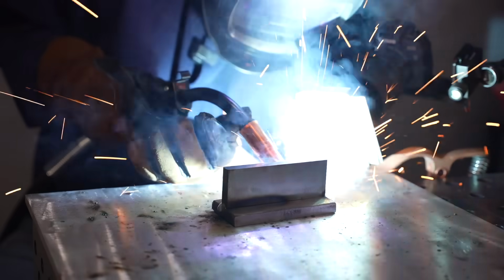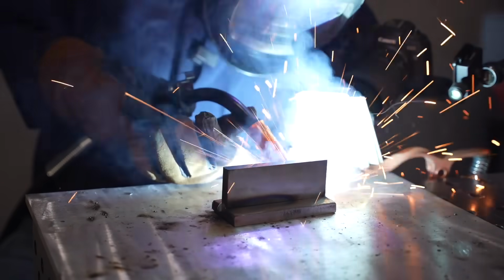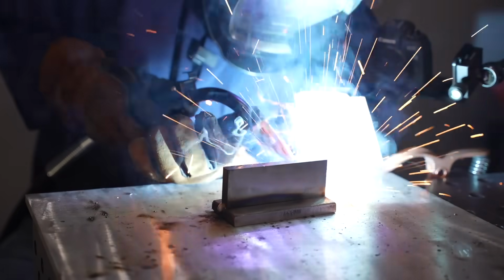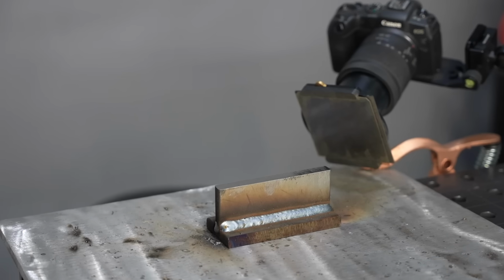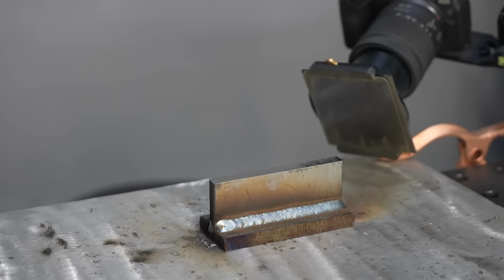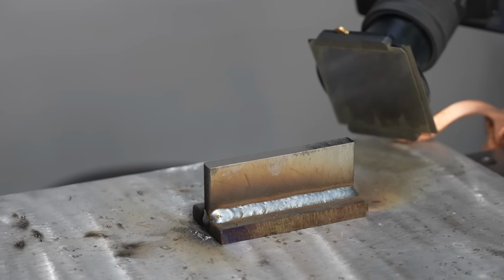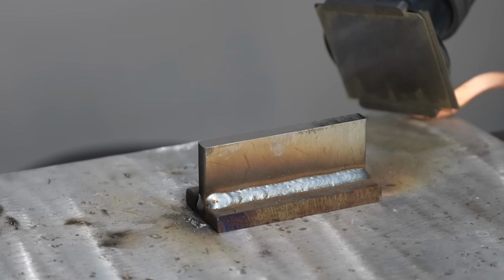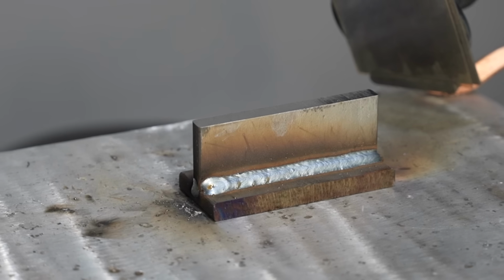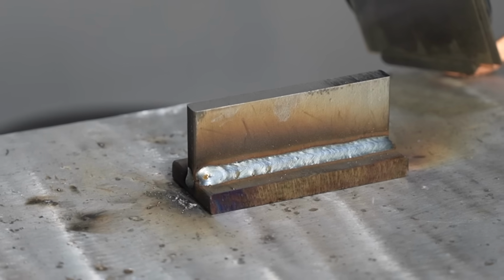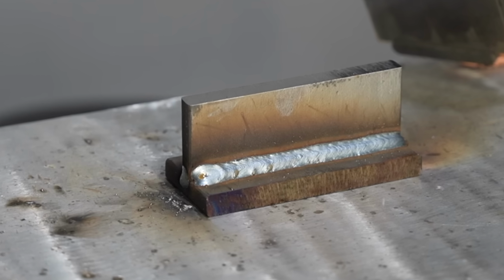Now I'll give a little disclaimer, this machine is more powerful than your typical 200 amp machine, and we're pushing more amperage than you'd be able to do. So the 300 amp HDP is really making it possible, but to show the capability of this diameter of wire, I think it's a good exercise. Now overall the bead looks good. There's often questions about lack of fusion when you're running short circuit MIG on thicker plate like this, and it's a valid concern, but if you have enough amperage and you're pushing a big enough wire, it can be done. We'll cross-section it later just to put everybody's mind at ease.